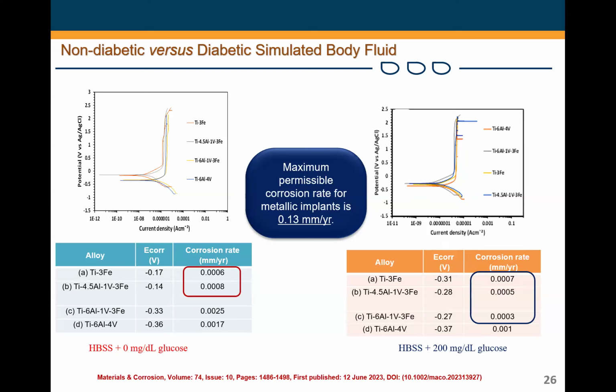The role of copper addition, the role of manganese addition, these are other alloying elements that have been explored in terms of corrosion and what happens in terms of the protective oxide layer. Those are not readily available in literature, and they are simple fundamental questions that I think people can explore and learn about. But from what we have done so far, what did we learn by adding iron to titanium? We found out that you can actually improve the corrosion resistance. We found out that iron seems to be promoting the thickness of the titanium oxide, and this explains why, in extremely strong acidic environments, for the iron-containing titanium alloys, especially with partial substitution, the corrosion rate is reduced substantially.